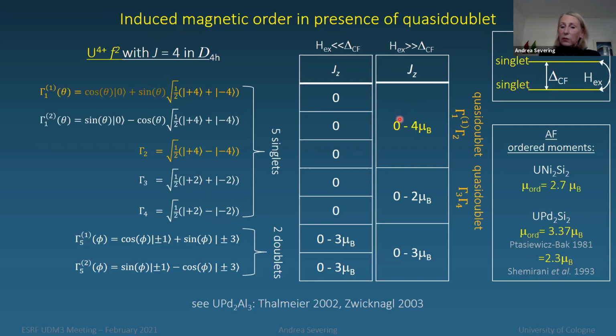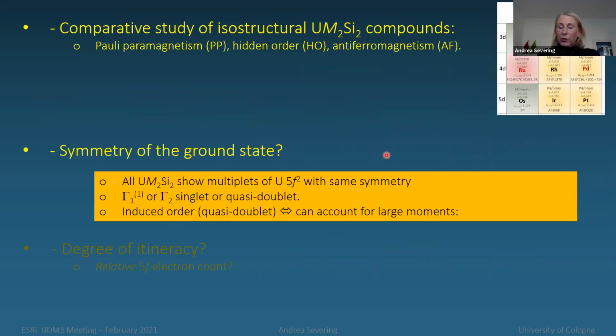So this is a very nice confirmation that our assignment of symmetry is right. I mean, these two singlets could also give rise to a quasi-duplet, but the moments would be smaller, and of course the doublets would account up to 3, but that we really can exclude from our INS data. So with this, we have settled the ground state symmetry. It's the same for all four compounds.